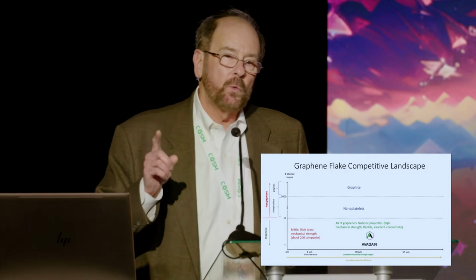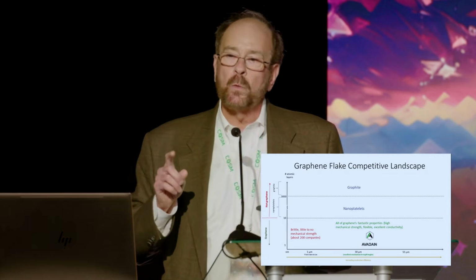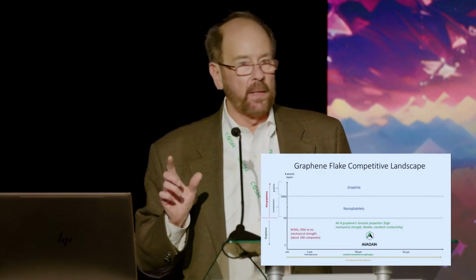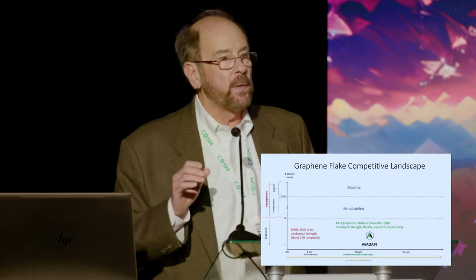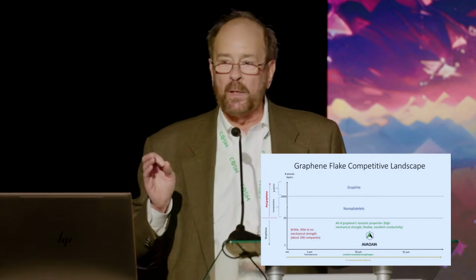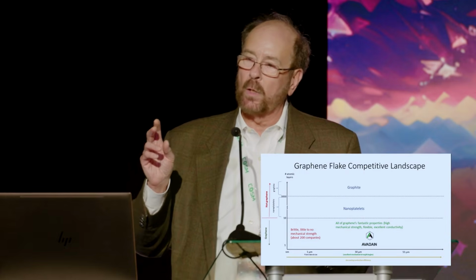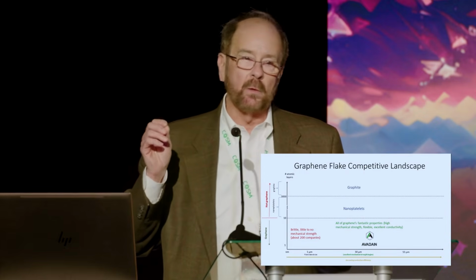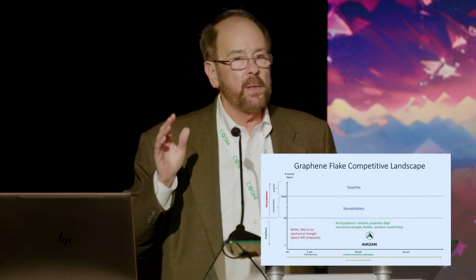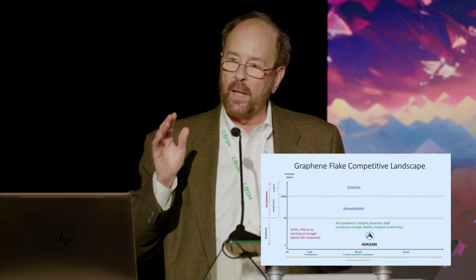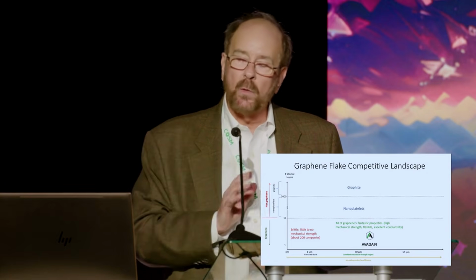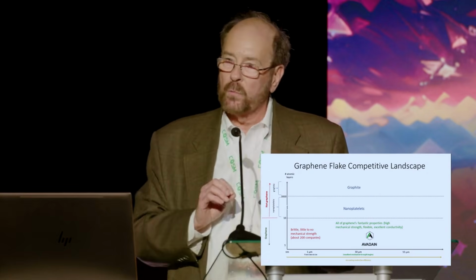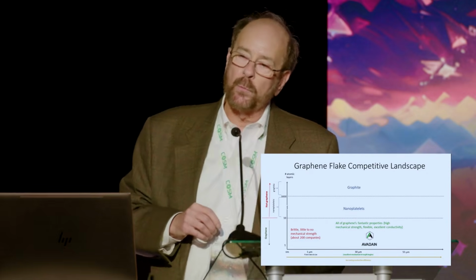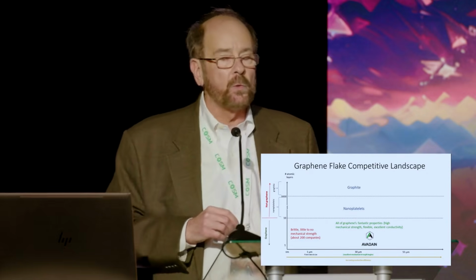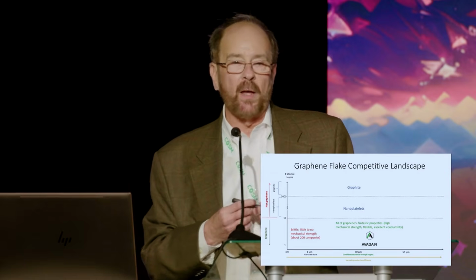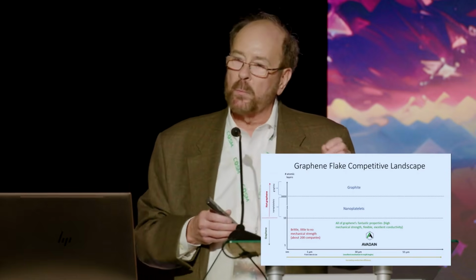But the key to graphene is the lateral flake size. What we find is that the optimal strength of graphene, being 200 times stronger than steel, occurs at 30 microns in lateral flake size. The lower you get, the more brittle the material becomes. And so when we look at graphene that may be in the 1 to 7 micron size in lateral flake, it becomes brittle as a material.